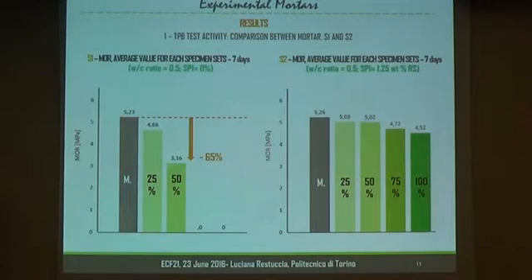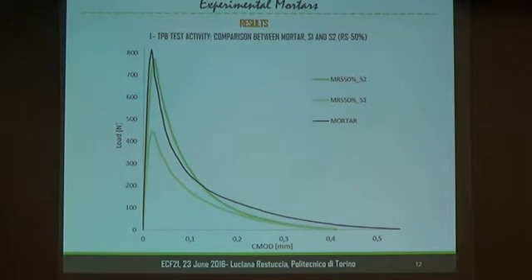in the percentage of 1.25% with respect to the weight of the recycled sand. And as you can see, in this case, we obtain good results, more similar to the reference mortar. This is a clear explanation that the reference mortar and the mortar with superplasticizer, in this case the dark green, are comparable in this load-CMOD curve, while the mortar without the addition of the superplasticizer has a decrease in terms of modulus of rupture, as said before.